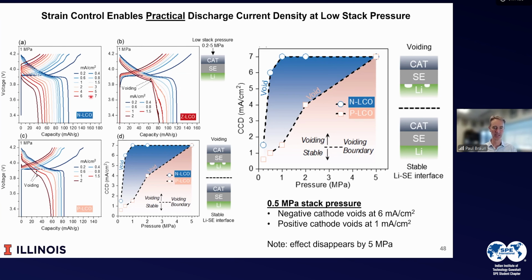And so here, if we look at 1 MPa stack pressure, if we design it so that the stresses oppose, after about 1.5 milliamp per square centimeter, there is voiding. On the other hand, we can go to much higher currents without voiding when the stresses are complementary. And this is important. While it disappears at 5 MPa, remember 5 MPa is 50 atmospheres. And so if I'm going to make a practical battery, I want to be working down here. And so what this means is that at very low stack pressures, which are practical, you can minimize battery failure by controlling the chemomechanics of the anode and the cathode.